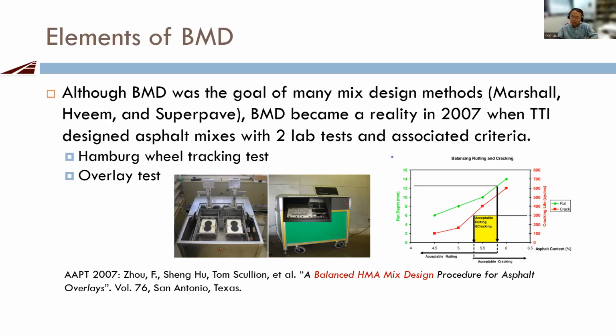You have multiple asphalt binder contents, like the green, the red line, this line, that's the cracking resistance. With increasing asphalt content, your cracking resistance gets better and better. And this green line corresponds to rut depths from the Hamburg wheel tracking test. Most states are still using half-inch as a criterion. So the blue line, if you cross this line, the intersection with this green line, that's the Hamburg wheel tracking test result. The more asphalt content you add to the mix, the higher the rut depth. So this intersection, coming down to this asphalt content, is the maximum asphalt content that you can add to the mix without causing a rutting problem.